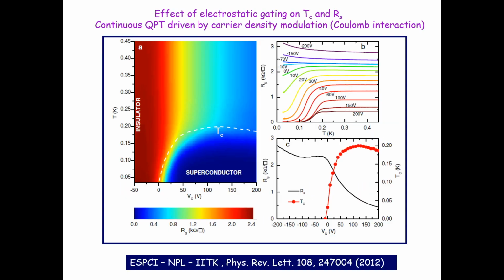Now, through our interactions with the French group, we started studying the effect of gating on the transition temperature. So let us start with a sample whose behavior at 0 gate voltage is somewhere here. You barely see a sign of superconductivity around 100 millikelvin. You apply gate voltage, make it more and more positive, the TC goes up and then comes down. So there is a sort of dome structure if I plot TC as a function of gate voltage.